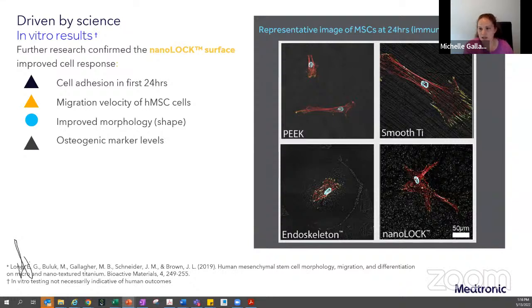The PEEK and the smooth titanium are these really elongated cells that are typical of fibroblasts and fibrous tissue, so fibrous encapsulation, which is commonly seen with PEEK. The endoskeleton surface started to change its shape and become more osteoblast cell-like, but the NanoLock surface at 24 hours had this stellate morphology, pretty much looks like a star, which is more typical of mature osteoblast cells. And then we also confirmed that all of these measures aligned with the osteogenic markers, similar to the previous study.